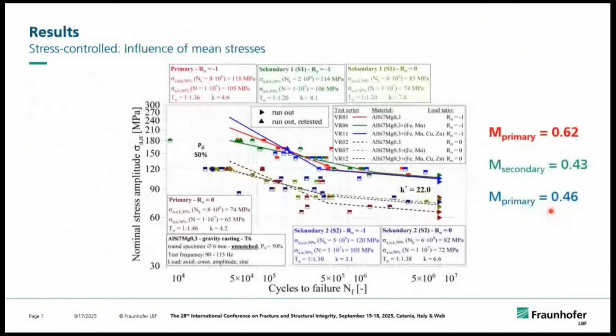When we look at the results, we start with the stress-controlled fatigue tests. The main takeaway from this picture is that we see on the upper side the alternating loading results, and the tensile loading results beneath that, for the unnotched configuration. Roughly, we can state that the difference in fatigue strength between the secondary alloys and the primary alloys is not really large.